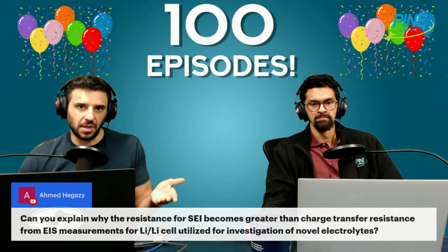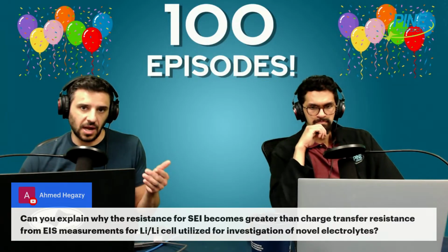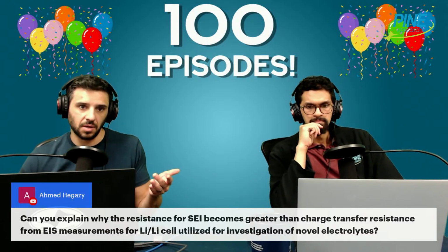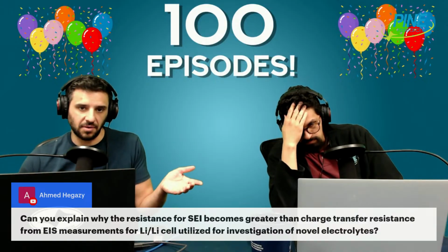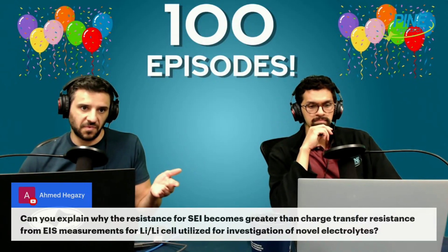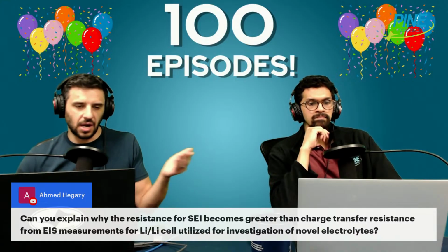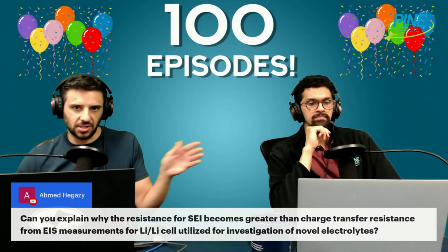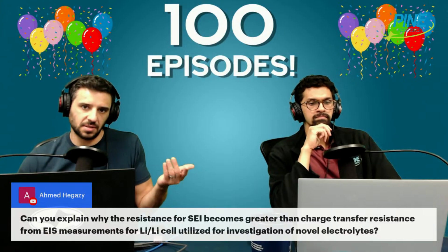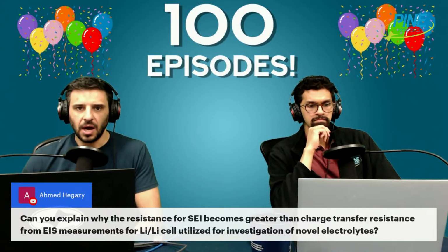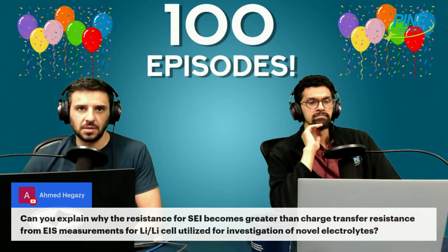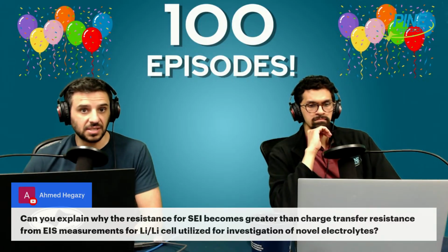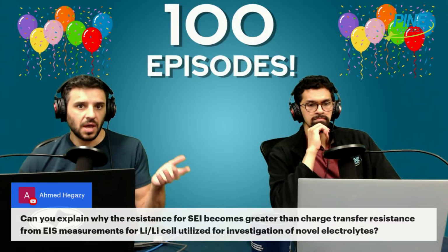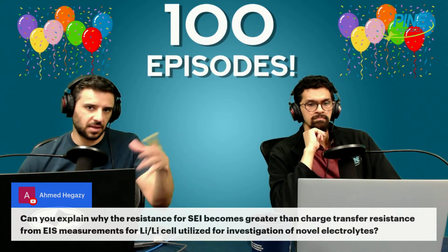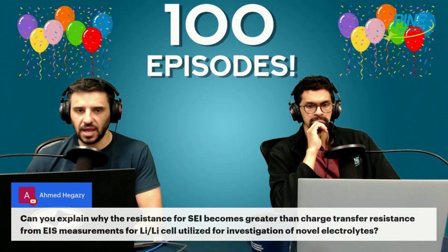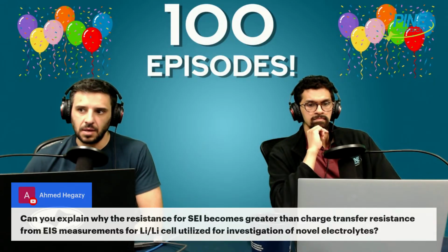It's one of the reasons why lithium as a metal by itself is not the greatest choice for an anode. Because you might ask, why don't I just use lithium all the time in batteries? And we don't, because one of the facile natures of its intercalation, deintercalation process is that it forms dendrites pretty easily, whereas other materials don't. And so part of that process might mean that its charge discharge characteristics and resistance are relatively low. And if you're starting to get some of those effects, thickening or secondary charge storage in the SEI, that might lead to the SEI growing in that way.